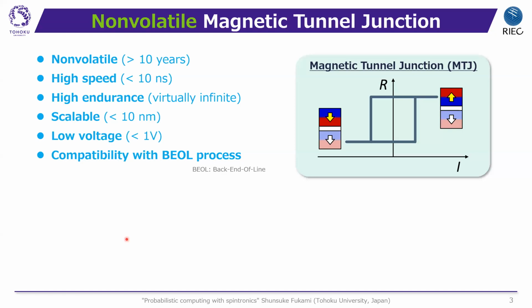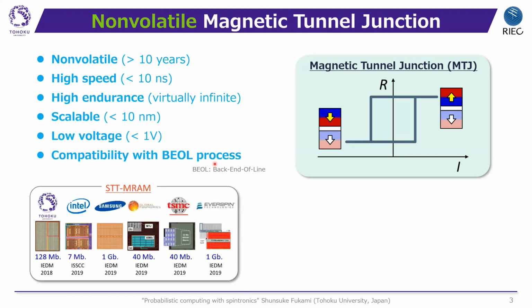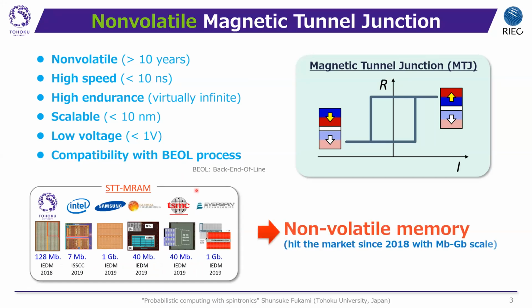I do not have to spend many words to explain the non-volatile magnetic tunnel junction because everybody knows it well. Magnetic tunnel junctions, or MTJs, can store information in a non-volatile fashion, and their state can be switched by applying current through the tunneling barrier. The magnetization direction can be switched by the current and detected by measuring the resistance. This can store information non-volatilely, operate at fast speed, has high endurance, is scalable, and can be operated with low voltage. It also has good compatibility with the back-end-of-line process of CMOS technologies. With these features, STT-MRAM has been commercialized since around 2018 with scales from megabit to gigabit.